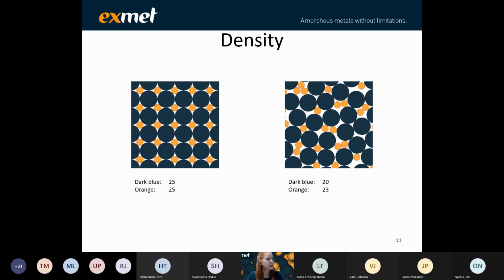If we look in detail and try to understand the atomic world, the crystalline material to the left has a higher density than ours. A normal steel has a density around 7.8, and our amorphous iron-based alloys will have densities of about 7.4 to 7.6, which can be explained by this less ordered packing of atoms. It's not as well structured, it's more random, and not as many big and small atoms, the dark blue and the orange circles, can be fit in a certain volume.